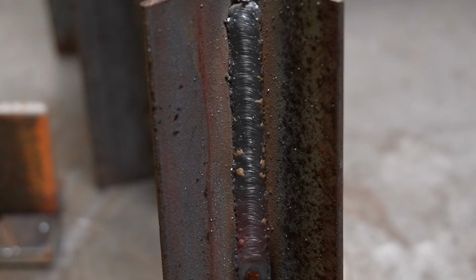But on the other hand, if you see the edges of your weld not soaking into the material and it's just laying on top of it, it's probably not penetrating enough and you're too cold. The weld might look good, but as you can see here, the edges just aren't really fused. And in reality, there's just no penetration behind this weld. So there's a fine line and a sweet spot where you're running hot enough to soak into the material, but cool enough where you can still control the puddle.